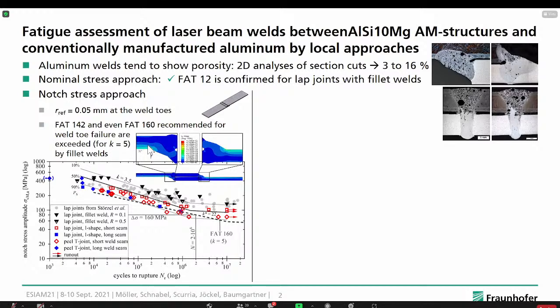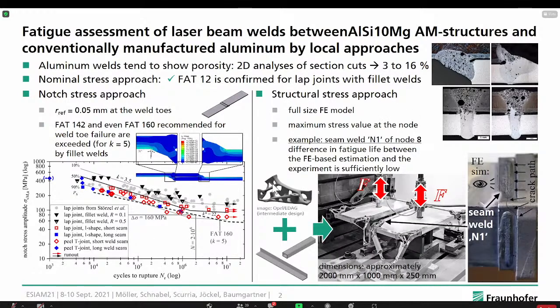So yeah, there is still some work to improve this process, for example, to include defect porosity into the notch stress approach. In a second step, there was a so-called battery carrier, which is used in the automotive industry for electric cars, as a component where additively manufactured connection nodes are welded to conventional aluminum sections, and this was tested also under biaxial loading conditions comparable to the application.